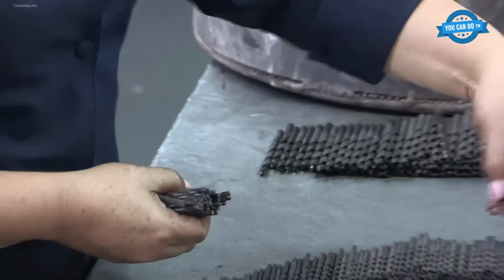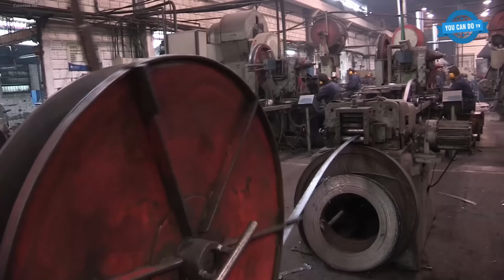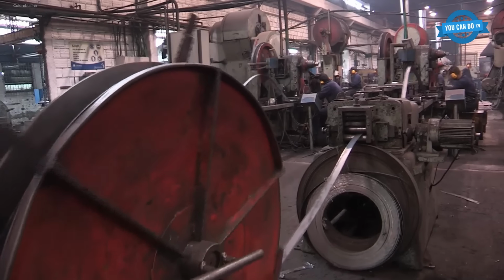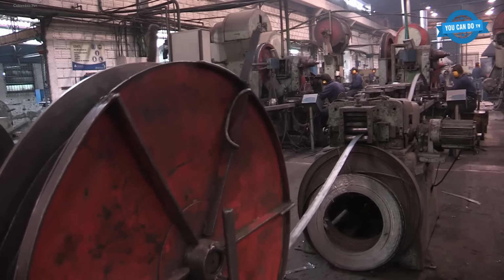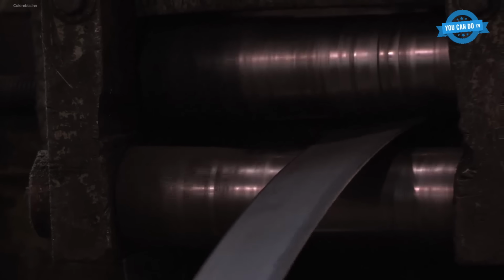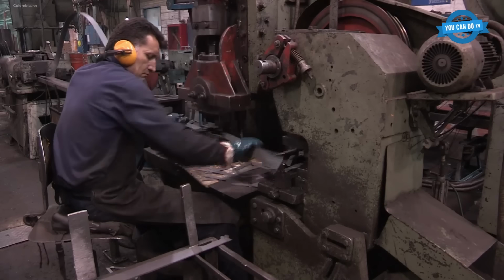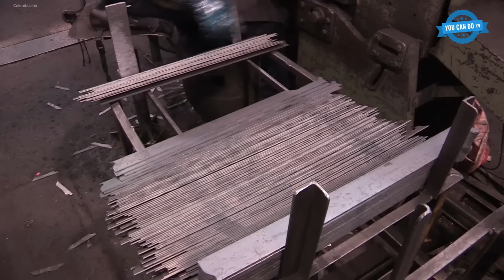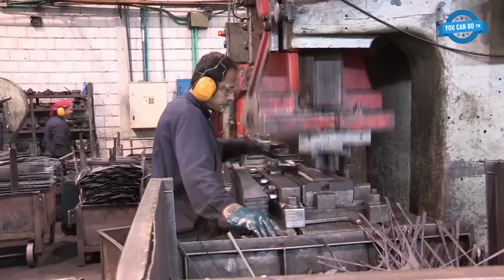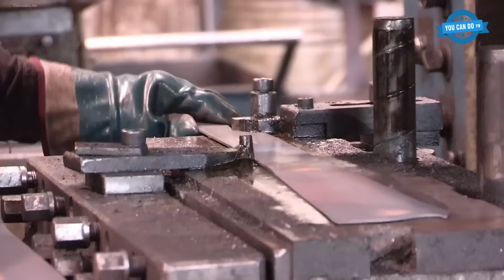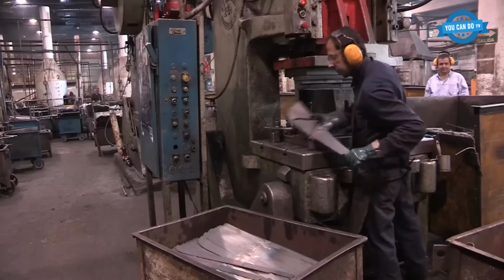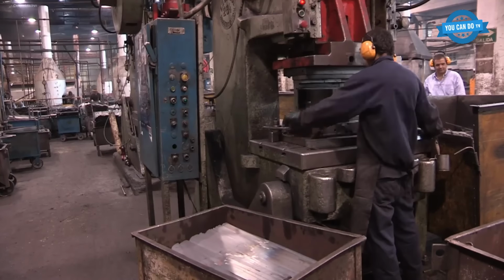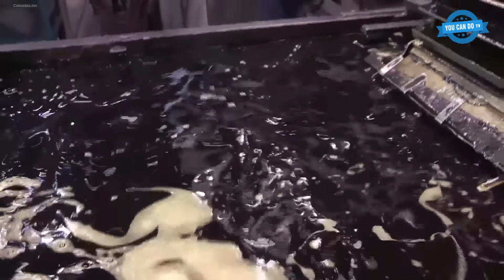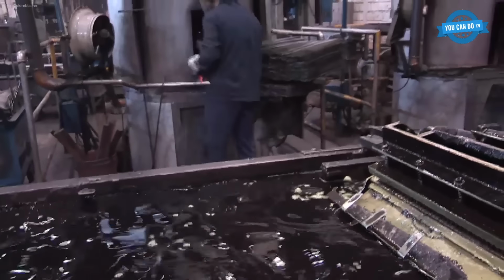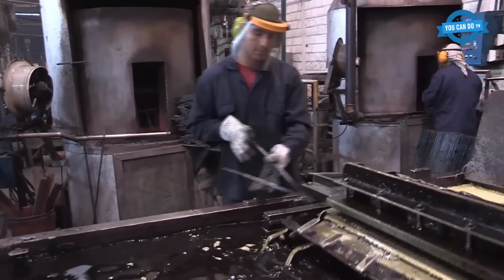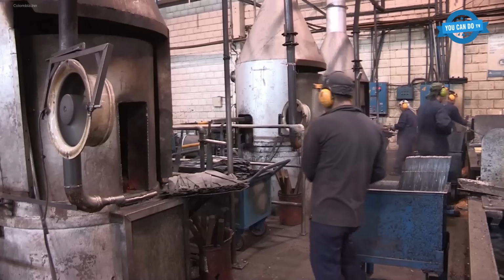The core of Colma's machete production begins with the procurement of high-quality steel, sourced primarily from England and South Korea. This steel is processed entirely in-house to maintain complete control over quality. Initial operations involve cutting and stamping the blanks, followed by a lamination process, a critical technical step that enhances grain orientation and blade integrity, inherited from the early German collaboration. The laminated blanks are then shaped, heat-treated through hardening and tempering processes, and undergo robotic polishing and sharpening to ensure consistent cutting performance.